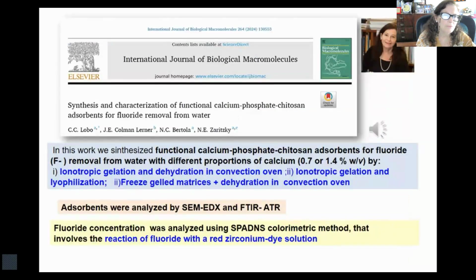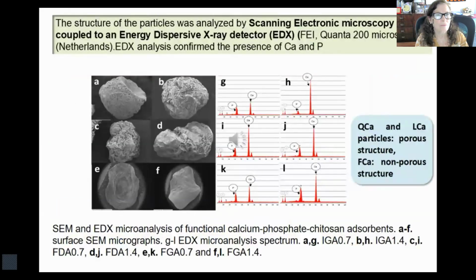In this work, we synthesized functional calcium phosphate chitosan adsorbents for fluoride removal from water with different proportions of calcium, by ionotropic gelation and by freeze-gelled matrices. Adsorbents were analyzed by scanning electron microscopy and FTIR. Fluoride concentration was analyzed using a colorimetric method that involved the reaction of fluoride with a red zirconium dye solution. We can observe in the figure the structure of the particles analyzed by scanning electron microscopy and the EDX analysis.